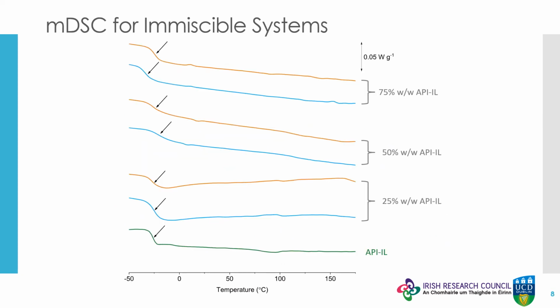The DSC thermograms for the immiscible systems exhibit a single glass transition temperature for all the ratios studied. Ordinarily, this would be taken as evidence of a miscible system. However, the behavior of the system is somewhat unusual, as even with high proportions of polymer, the single TG is remarkably close to that of the pure API-IL and shows no dependence on the composition of the system.